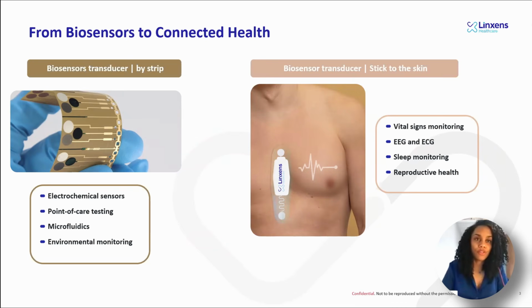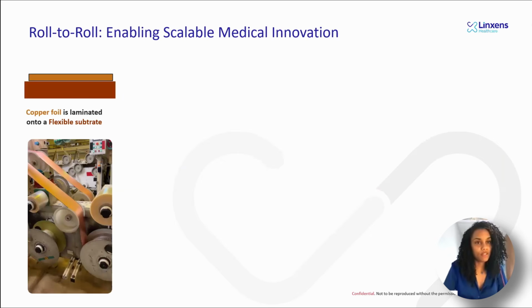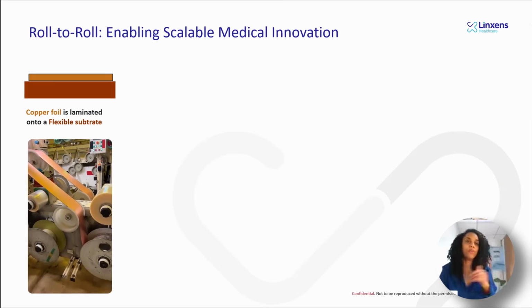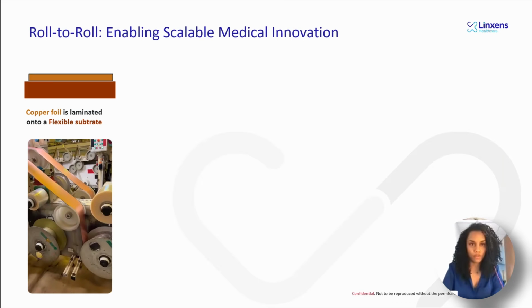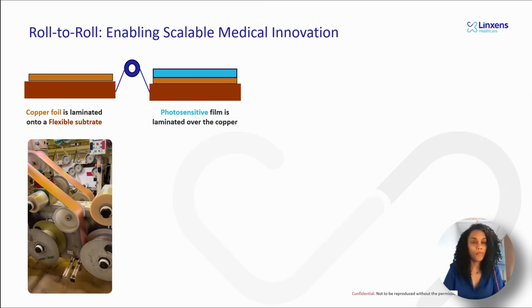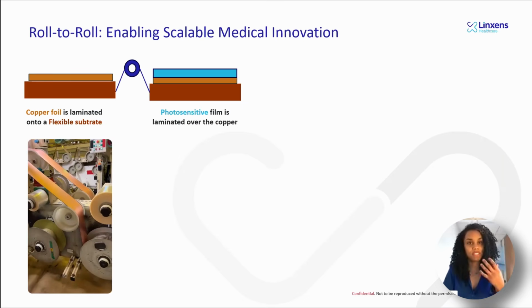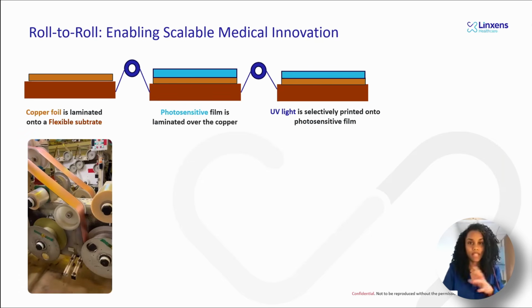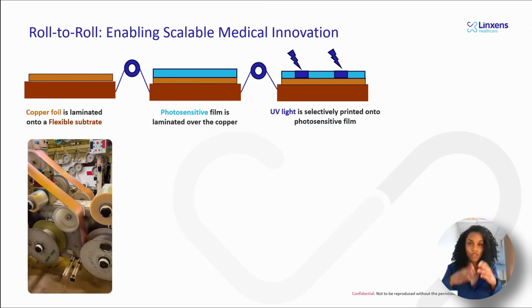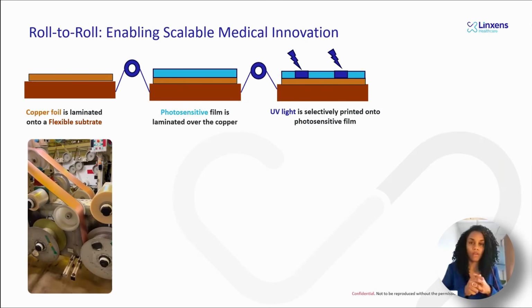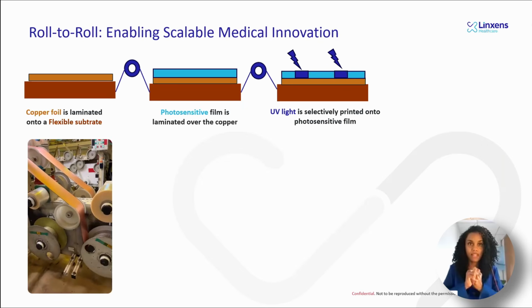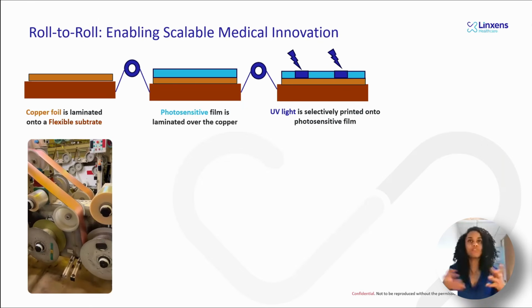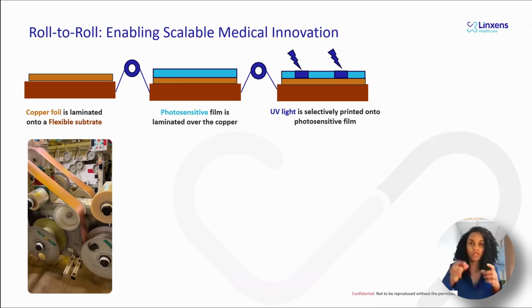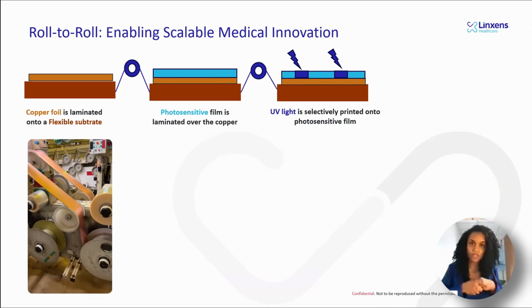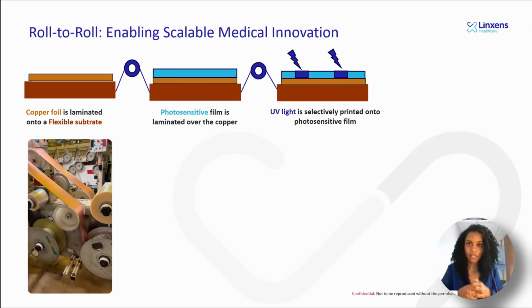So let's see for the strip version what the manufacturing process is. We start the manufacturing with the lamination of a copper foil onto a flexible substrate. On this copper foil, we will laminate a photosensitive film. After that, we will send UV light on a selective area to print the design that the customer wants. For example, if the customer wants a circle or a square, the UV light will come at the surface of the photosensitive film to print this pattern.